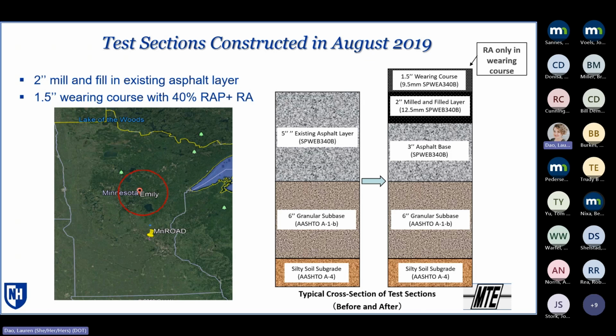So it was a 5-inch asphalt layer that had 2 inches of mill and fill, and then a 1.5-inch wearing course put down on top. And the wearing course had 40% RAP plus each of these different 7 materials, and then there were control sections that went along with it. So the RA section materials are just in that wearing course.